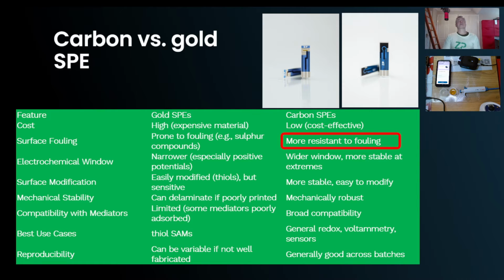But gold is considered an inert material. Relative to carbon, I'd actually say that gold is less inert than carbon. And that comes up in the second point here: anyone who's worked with a gold electrode knows that in some liquid environments, gold is quite easy to strip. You're increasing the positive potential and suddenly you get this stripping potential. And then you may come back, if you're doing cyclic voltammetry, and you'll get this deposition event. So you're stripping gold and making the gold 3+ ion, and then you're plating the gold 3+ ion back onto the electrode. So it's not the electrochemically stable material that people necessarily think it is.